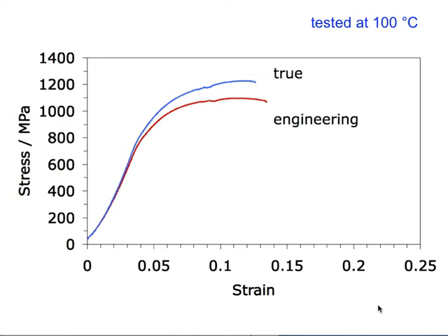And we get this, on the same scale as the previous slide, and you can see that the elongation has dropped dramatically, and if you look at the amount of austenite at the beginning and at the end of the test, then you can see that it's not really contributing to the work hardening, which leads to a greater elongation. So it's a very simple experiment that you just alter your tensile test temperature by 100 degrees centigrade to stabilize the austenite, and you can prove that it's actually playing a role in controlling the work hardening capacity, and therefore the point at which you get necking in your material. Is everyone happy with that?